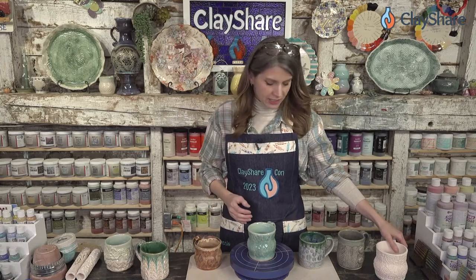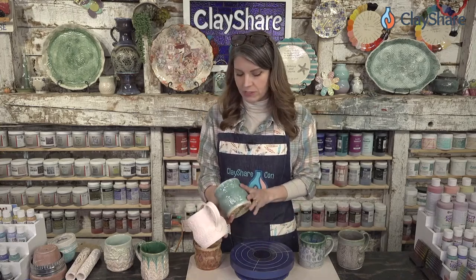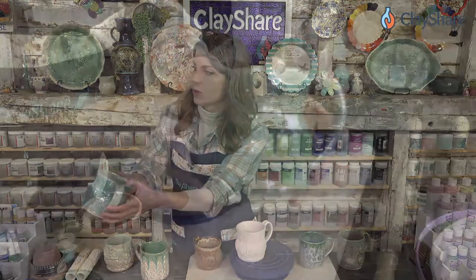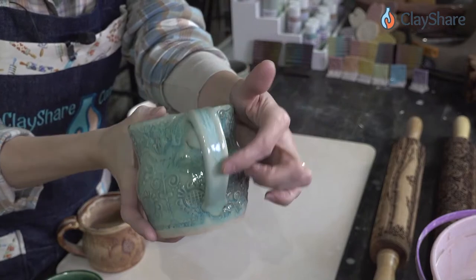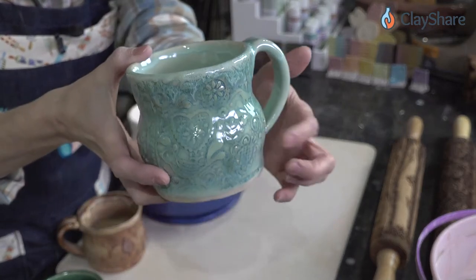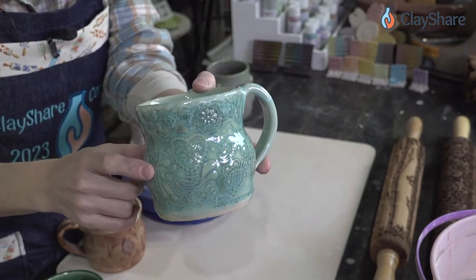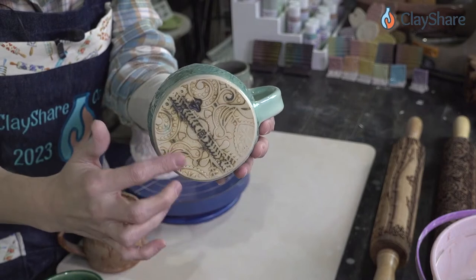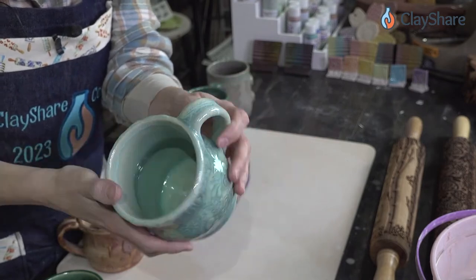In the image I used for tonight you've seen this mug here, and here's another one that was in the image — glazed. The third one from that picture sold. This one is glazed with Georgie's Interactive Pigment Sand and Surf, and then the glaze on top is my Chun Blue. The Chun Blue by itself looks like this; when you put light flux on top you get this effect, and when you put it on top of a pigment like Sand and Surf you get this deeper look. The pigment is applied watered-down, wiped back, stains the surface, and then you put your glaze on top.